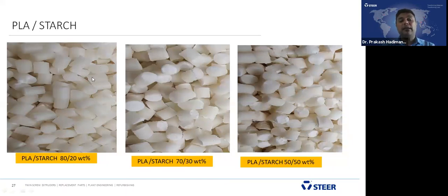When it comes to the PLA and starch, we have already explained. I already explained about the PLA. PLA is brittle in nature, but we are getting better tensile strength and flexural modulus. Addition of 20% starch gives better dispersion. You see no change in the black particles, nothing.